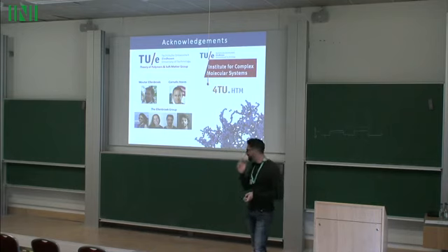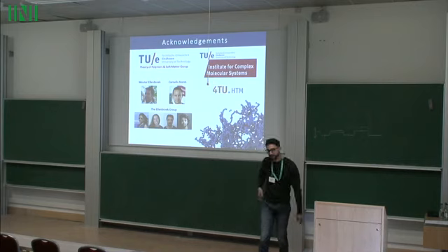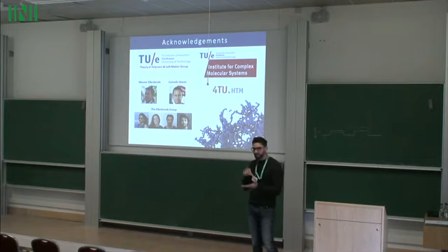But there's some other evidence that I didn't have time to show from Constantino Creton's group at ESPCI, where they keep the same chemical construction of the reversible crosslinks, but they vary the strain rate. They find that when they strain very, very slowly, that is the regime where they see the most toughness enhancement with the smallest change in the elasticity, which would imply that you're in this quasi-equilibrium regime, and so you're letting the things equilibrate and cluster. If you strain faster, then your modulus gets stiffer.